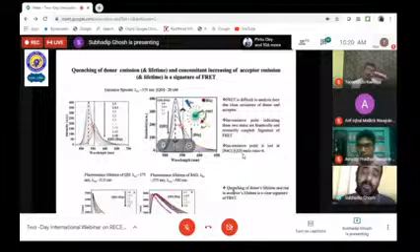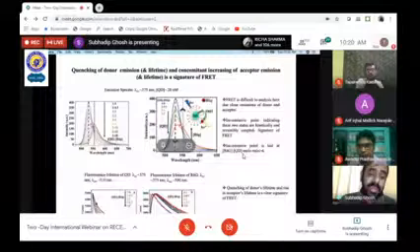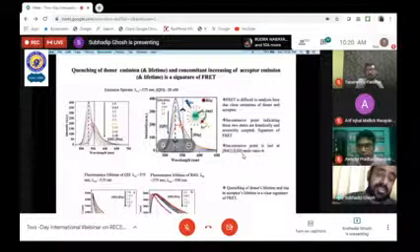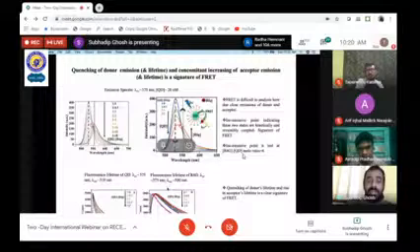And now if we look into the fluorescence lifetime profile, which we measure in TCSPC, we found that donor emission is quenched at the cost of a rise coming in the acceptor's emission. This rise indicates again that FRET is taking place.